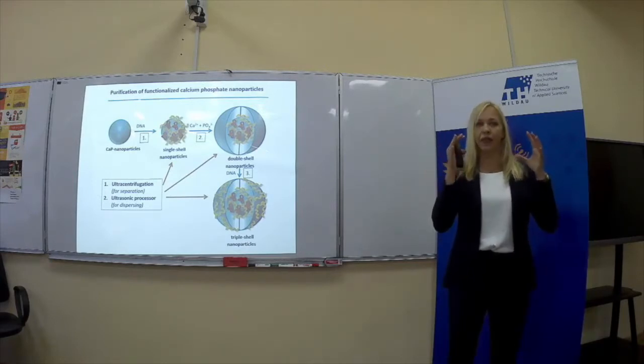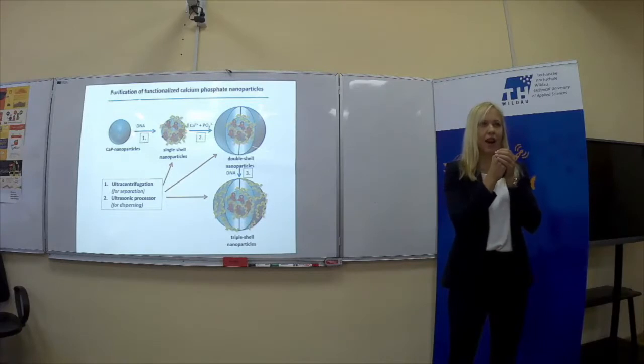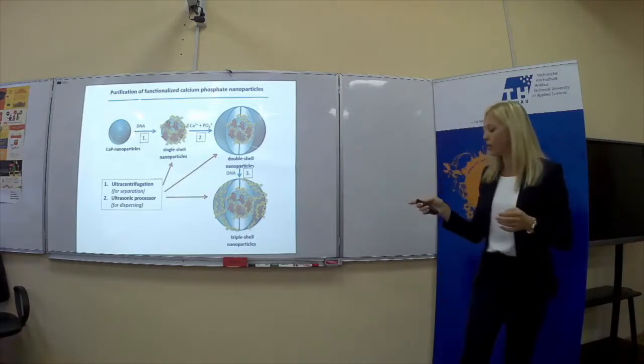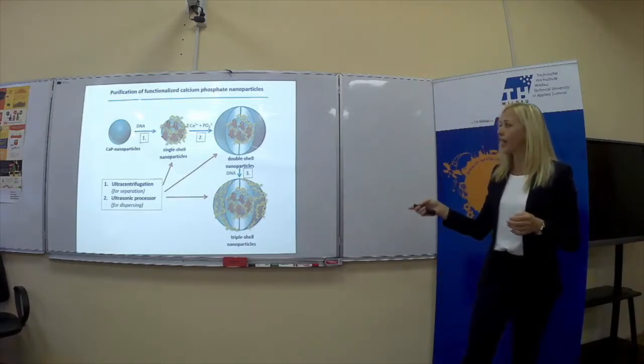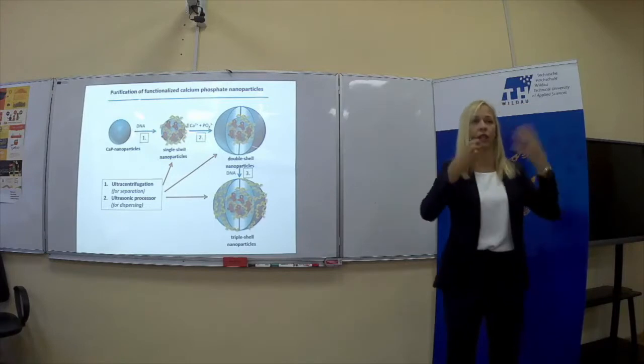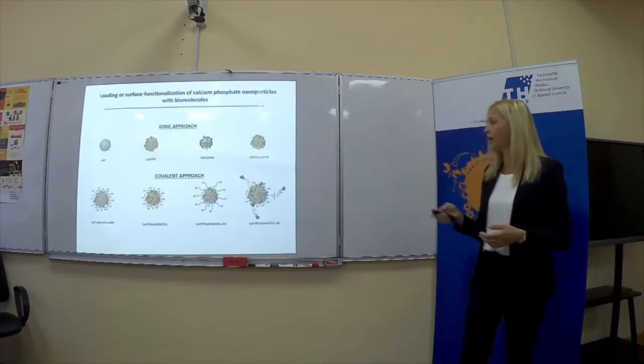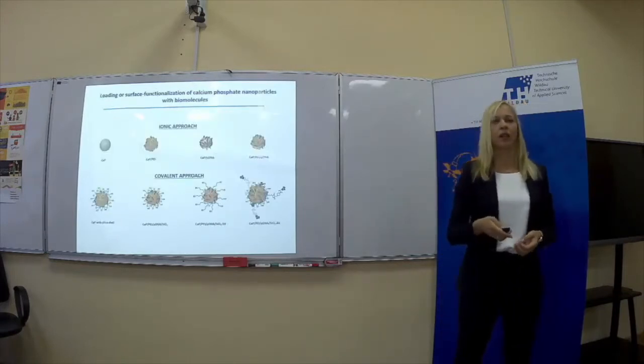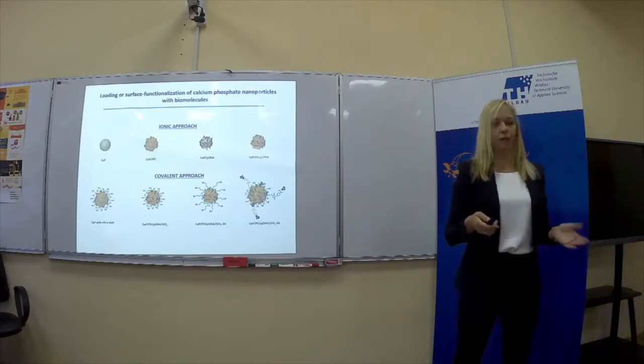Because after centrifugation, the nanoparticles are pressed together and with shaking, you cannot take them apart. For this, you need an ultrasonic processor. So after each step, you just centrifuge and you redisperse. And at the end, you have really great nanoparticles. Talking about calcium phosphate nanoparticles.